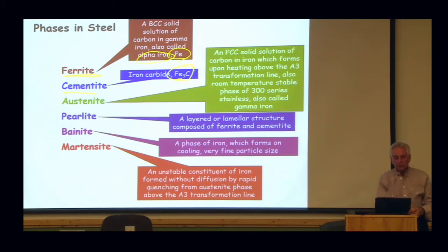Now, we can take that piece of steel, put it in an oven, bring it up above the 1333 degree temperature and we can say now it is austenitic or you can call it austenite if you want to. Guess what? No matter, you can't get in there and use it for nothing anyway. You can't be welding on it. It's up in that oven. 1700, 1800 degree. But it's got to come out. And when it comes out, it can come out if I shut the oven off and let the oven cool back down real slow and then take it out after it cooled and whack me a piece out and blow it up under a microscope, that would be called pearlite. Slow cooling gives me a layer that looks like a thumbprint under a microscope.